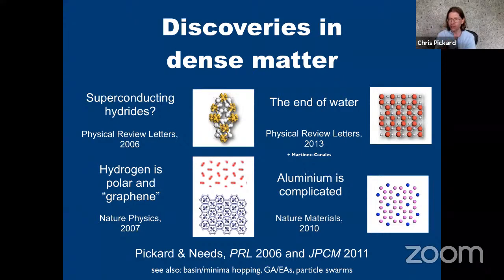If you squeeze water to the pressure at the core mantle boundary in Jupiter, actually H2O is not a stable composition. It'll decompose into hydrogen peroxide and a hydrogen rich phase, which is quite closely related to these superconducting hydrides. I also found that if you squeezed aluminium to high pressure,